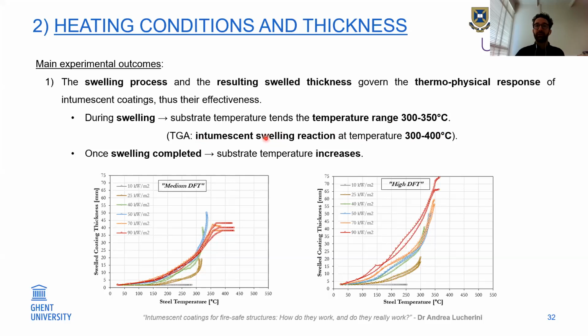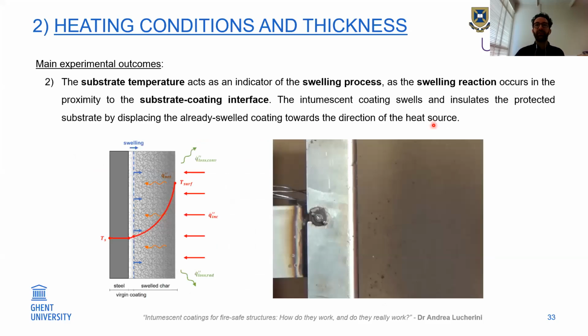So when the coating is swelling, the temperature of the substrate, which is behind the coating swelling, is below the reaction temperature. That makes sense. And once the swelling is completed, the substrate temperature increases above this threshold. So this gives us a very important understanding of how the intumescent coating swells.